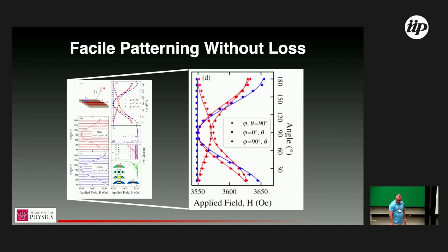For the blue here, looking at the disks, the blue data is exactly the data that I showed here, the one in the triangles, and then the circles that don't vary, where the magnetic resonance doesn't vary, is in plane. So we have no in-plane anisotropy for a disk, which is what you would expect from the shape, but it also highlights that there's no crystal field anisotropy either. But the red curves are a little more complicated. You have something that tracks more or less with the blue curve, in plane to out of plane: disks and lines look the same, but in plane you have some variation.